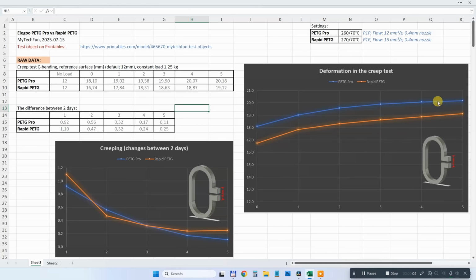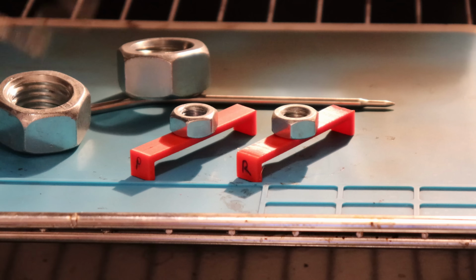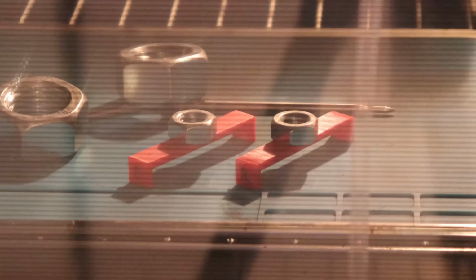On this graph we can see the deformation distance between two reference surfaces, and we can see less deformation on the rapid PETG. But the creeping is the difference between 2 days, and that's what we can see on the second graph. And more or less we can see some difference here, but I would say that these are very similar for the creeping.